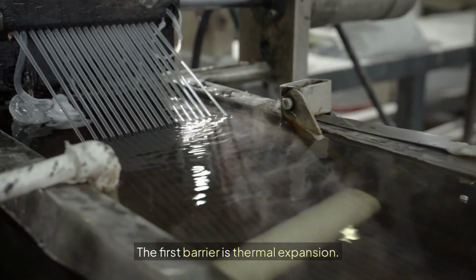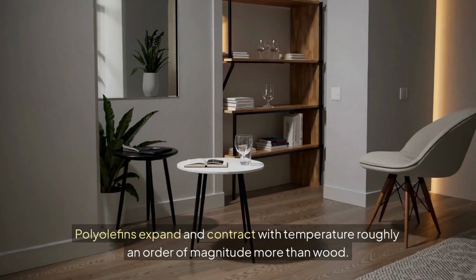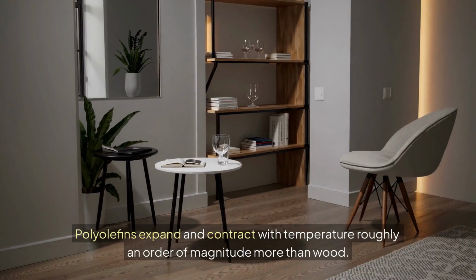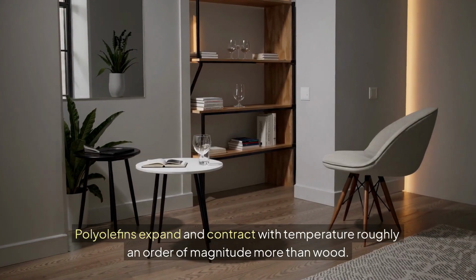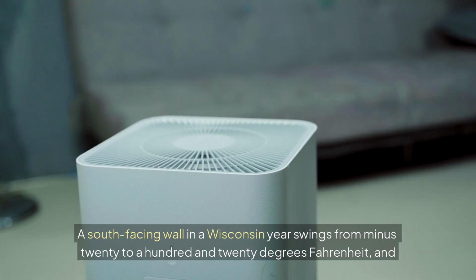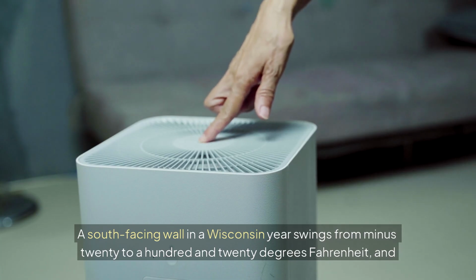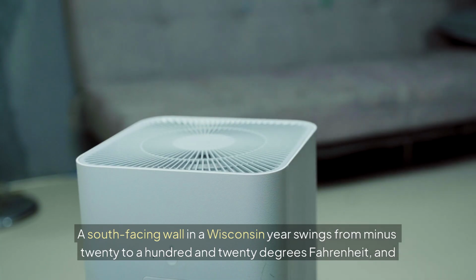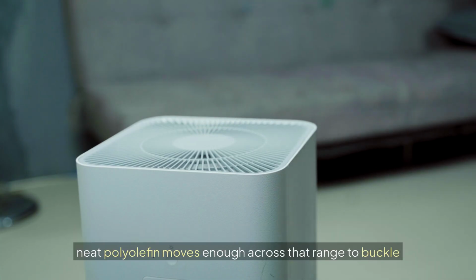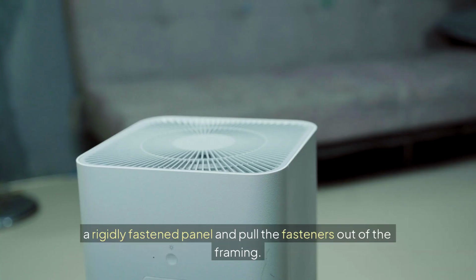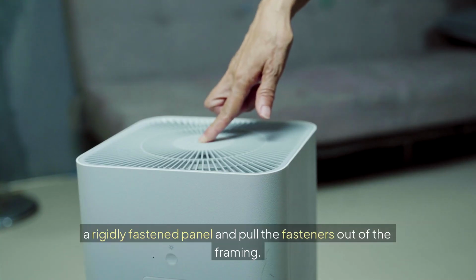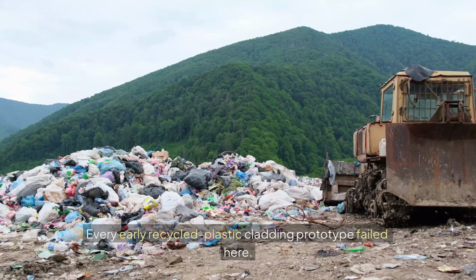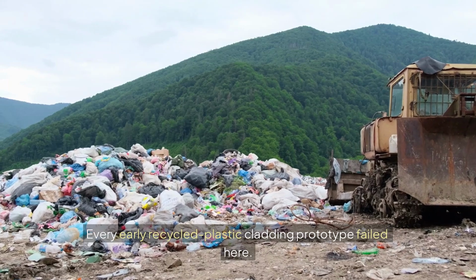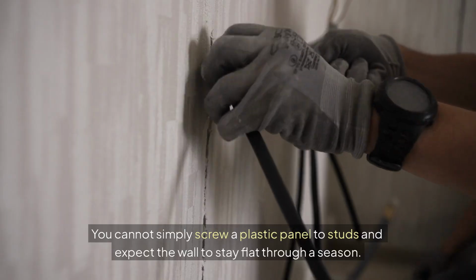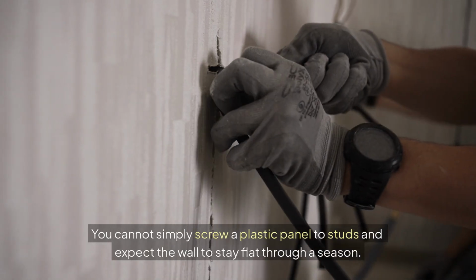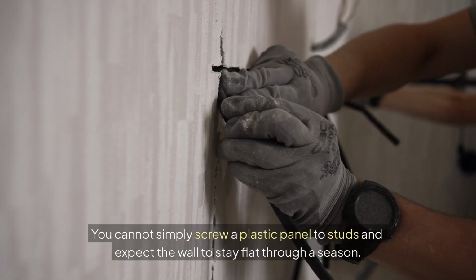The first barrier is thermal expansion. Polyolefins expand and contract with temperature roughly an order of magnitude more than wood. A south-facing wall in a Wisconsin year swings from -20 to 120 degrees Fahrenheit, and neat polyolefin moves enough across that range to buckle a rigidly fastened panel and pull the fasteners out of the framing. Every early recycled plastic cladding prototype failed here. You cannot simply screw a plastic panel to studs and expect the wall to stay flat through a season.